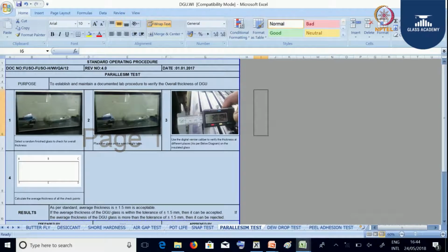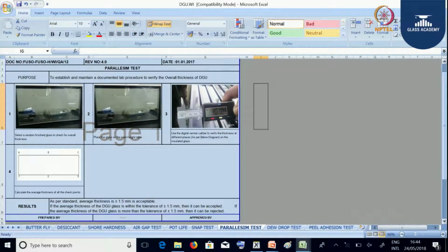Next test is the parallelism test, used to measure the overall thickness of the DGU. What we do is place the DGU vertically, and at the edges or at the center of the 4 edges we measure the thickness of the glass. Generally the thickness of the glass includes the individual glass thicknesses and the air gap the DGU is covering. As shown in figure 4, we measure the overall thickness at areas A, B, C, D, E, F. As per standard, the thickness difference shall be plus or minus 1.5 mm acceptable.